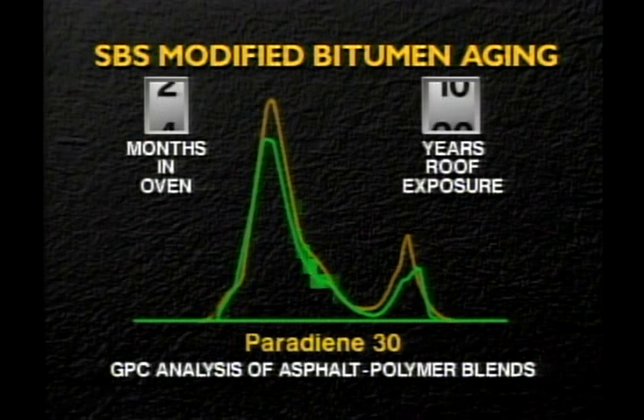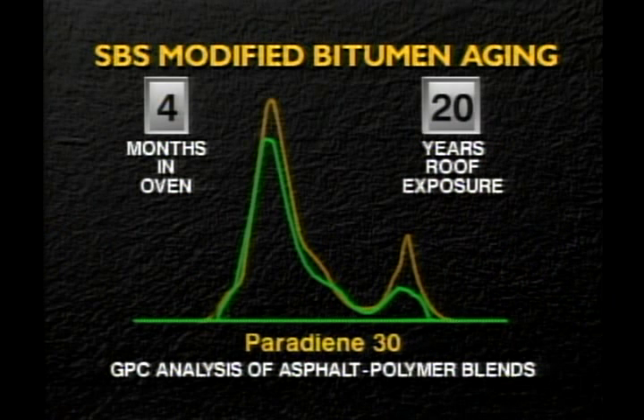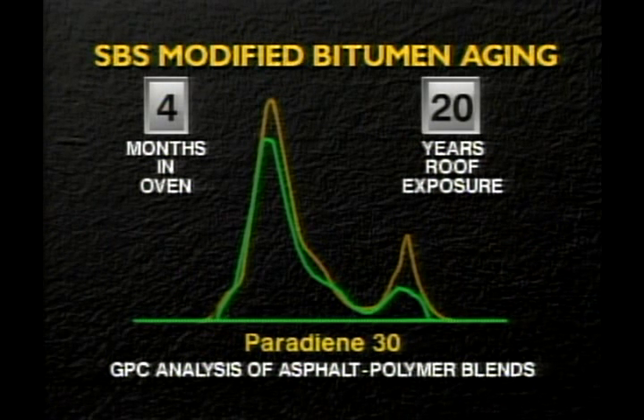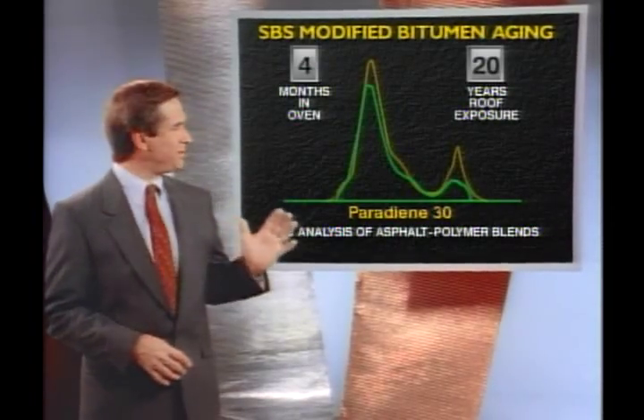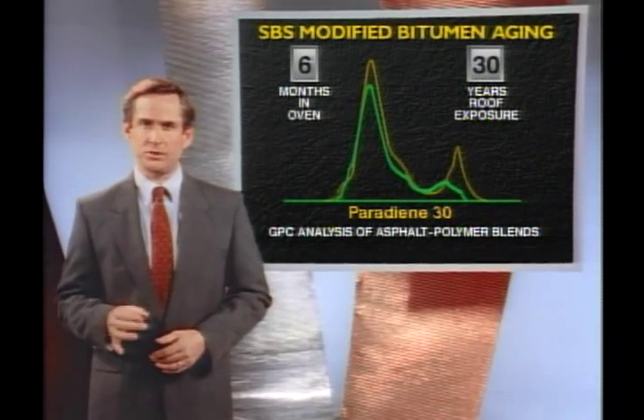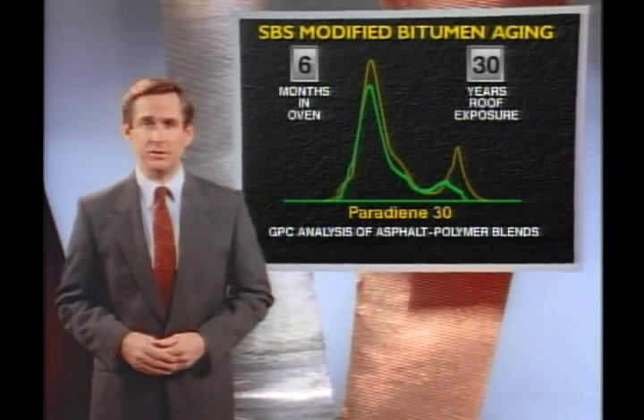After 4 months in the oven, the equivalent of 20 years of aging, the polymer peak is showing signs of age, yet is still performing well within specifications. No other company in the United States can validate this kind of aging proficiency through on-roof experience. No other company has over 20 years of experience with SBS-modified roofing. In the lab, after 6 months in the oven, Siplast can project a life expectancy of 30 years on the roof.